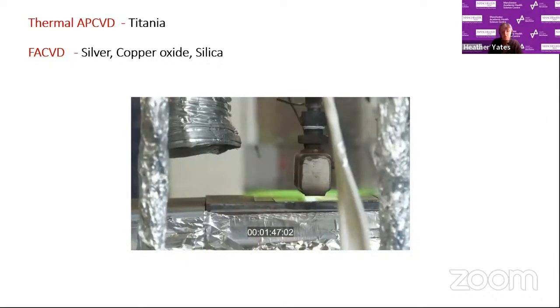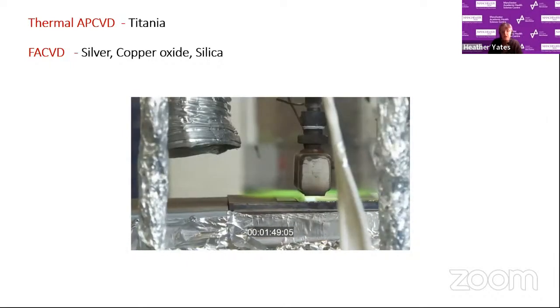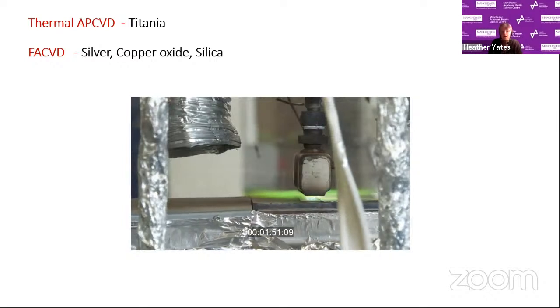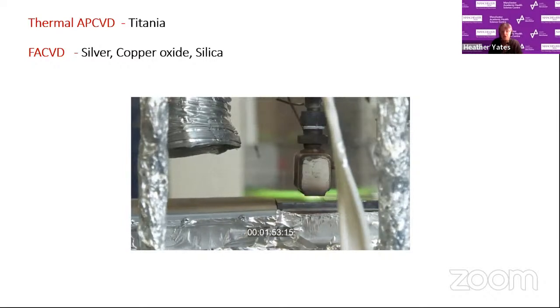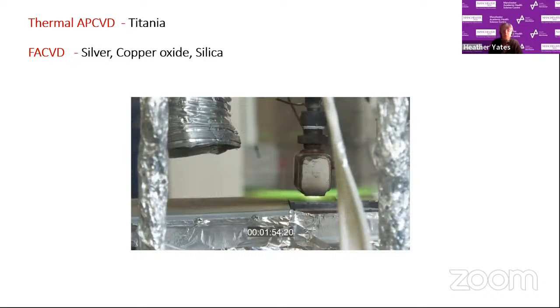And that passes over my material. In this case, I'm coating glass. And it can go forward and back. The number of passes just increases the thickness of the film.